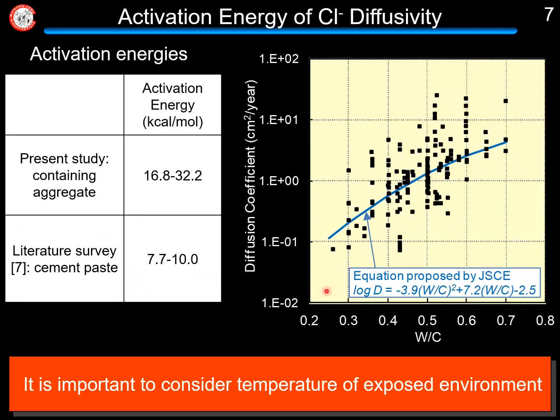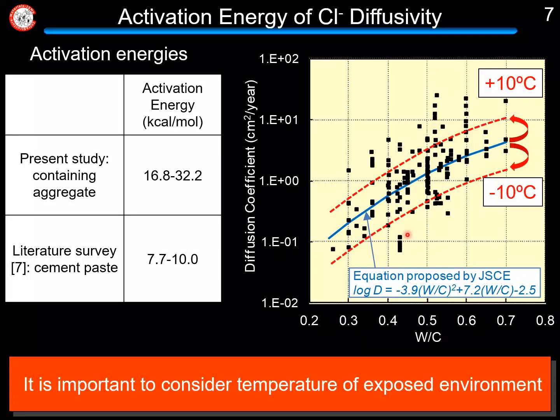The right side shows the relationship between chloride ion diffusivity of concrete and water-cement ratio proposed by the JSCE standard specification. And the broken line in this graph shows the chloride ion diffusivities considering a plus-minus 10 degree difference against the JSCE equation, using the obtained apparent activation energy.